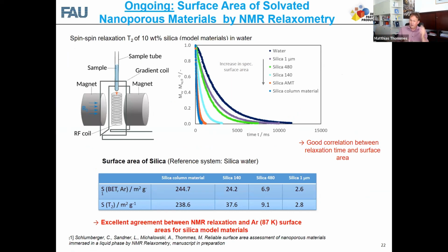And there are not too many options we have. One of them, which we now look at very carefully and very rigorously, is the application of NMR relaxometry. What you do here is put a sample in a very weak magnetic field, switch this on for a very short time, and then, if you do proton NMR, the protons go out of their place, you switch it off, and then you see how the protons relax. You can do spin-spin or spin-lattice relaxation observations, and this is, for instance, for the spin-spin relaxation.